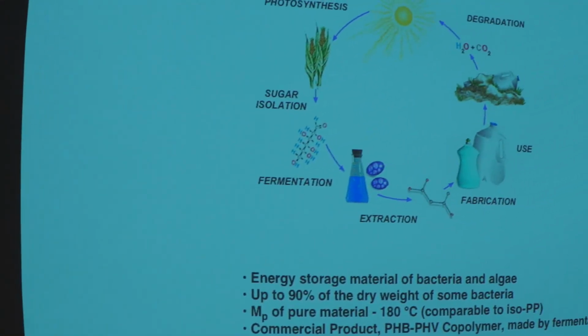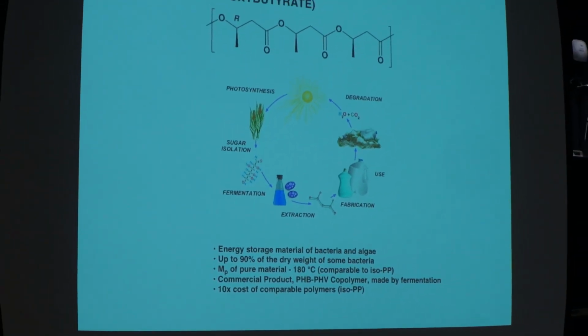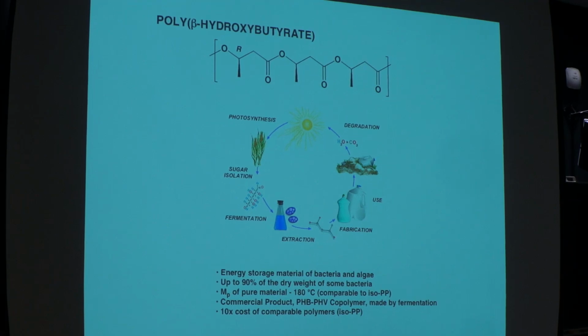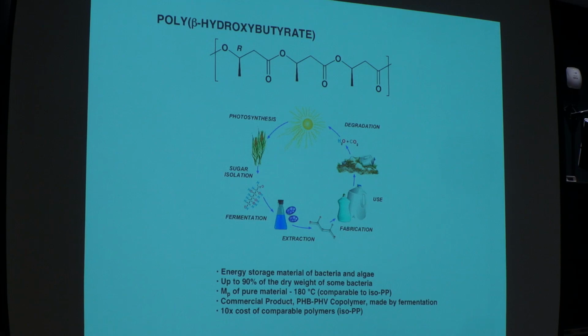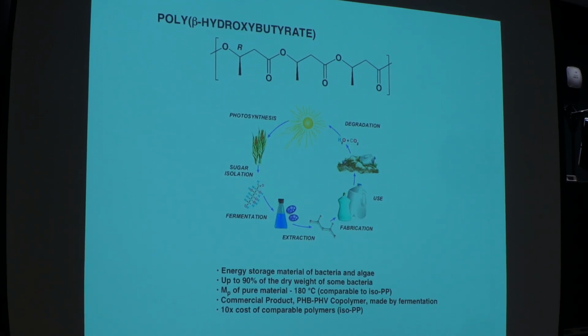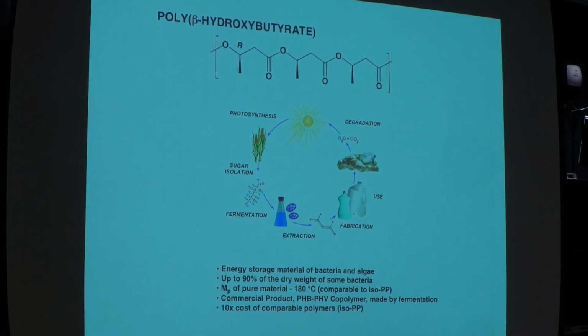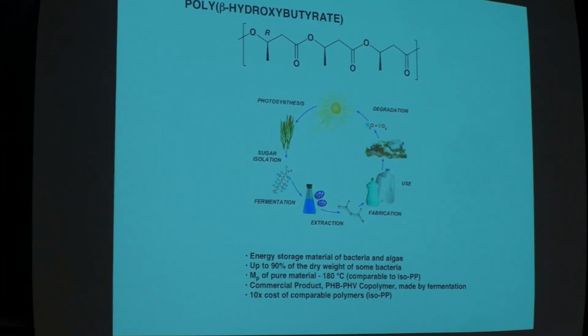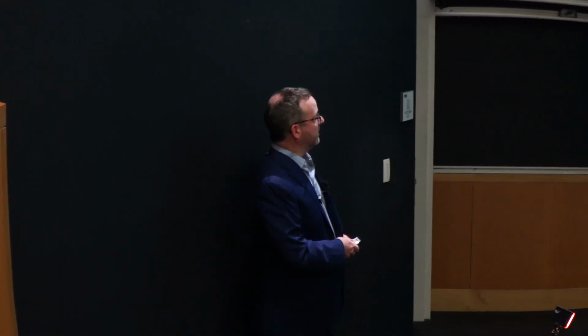So these have been made for a while. There was a company in Cambridge called Metabolix, and my understanding is that their stock is now at zero. They worked for a long time to make these by fermentation. The problem is that you first have to grow the corn, and that uses a lot of fossil fuel. You then have to have a very capital-intensive and energy-intensive fermentation process. It's also slow. It's a really expensive fermenter, and you have to wait a long time. Ideally, it makes some polymer that you're hoping to sell at 50 cents a pound. We're not making some life-saving pharmaceutical compound, they're making plastic. And so these materials cost, I would say in the best case scenario, about an order of magnitude more than polypropylene. And unfortunately, there's only a certain number of customers who are willing to pay more for a plastic that they deem better for the environment.